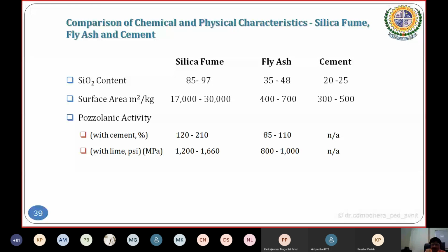Fly ash is written as very fine, but for silica fume you can look at 17. It was earlier written 13,000, here 17 is written, but the higher limit you can see is 30,000. So as far as pozzolanic activity is concerned, that is also very, very important. For cement the data is not collected, but for fly ash and silica fume, with this percentage and with lime, the MPa comes for silica fume as 1660, remember, very high strength, and then 800 to 1000 in the case of fly ash. This is the reactivity result as per IS 1727.